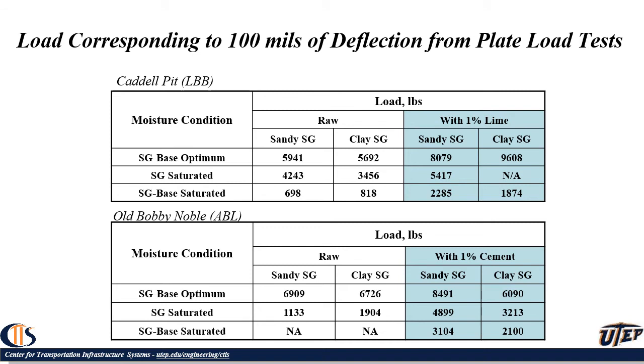We tested each specimen in 3 conditions: when the subgrade and base were placed at the optimum, when the subgrade was saturated, and when the base and the subgrade were saturated. And you see that, for instance, by adding 1% lime, we can significantly improve the performance of the material for this Cadell pit. And the same thing you would see, we can improve significantly with 1% cement the Abilene material, as you see over here.